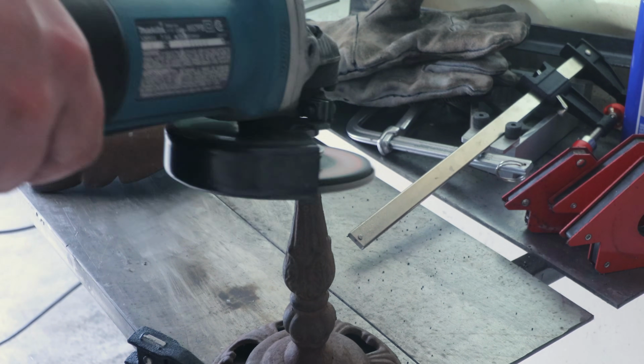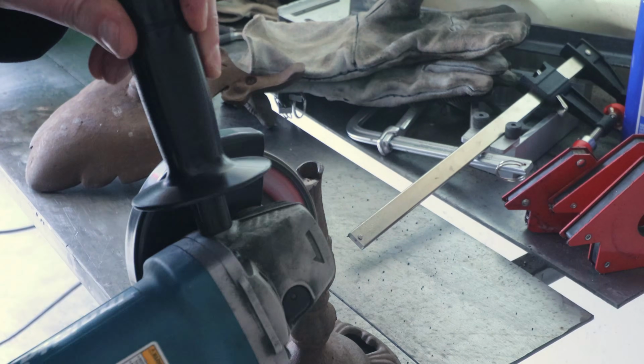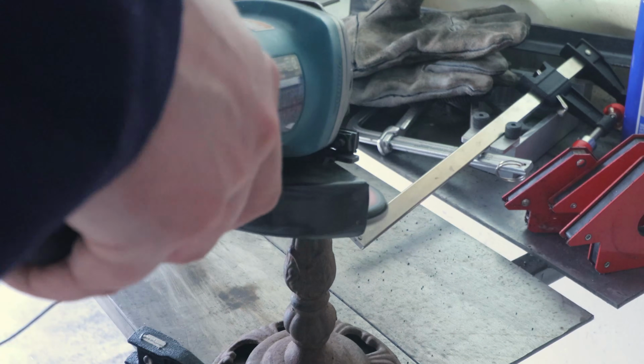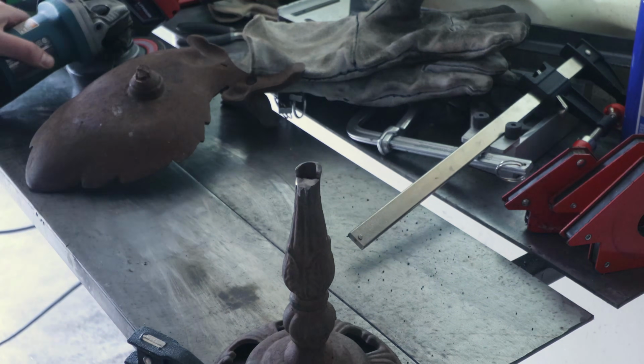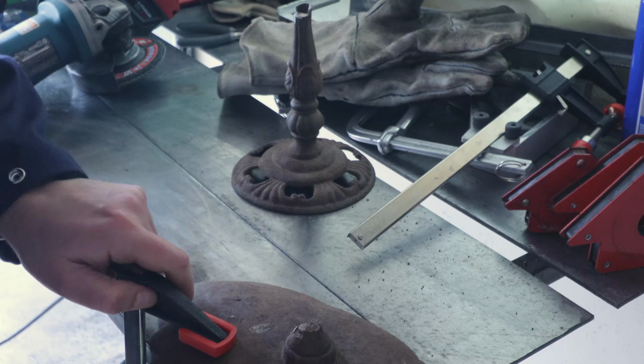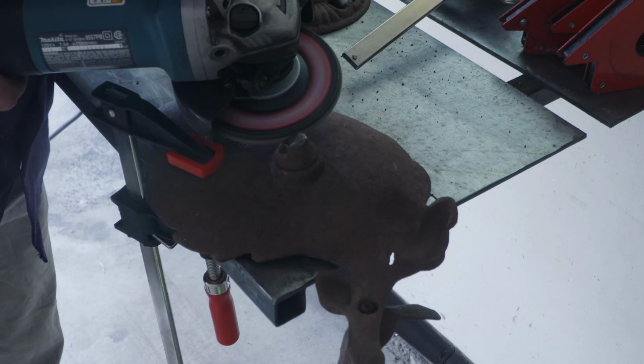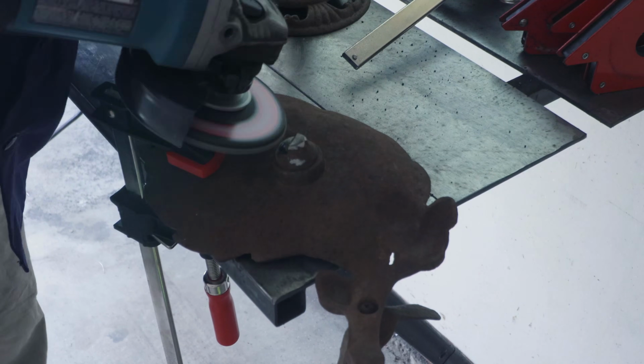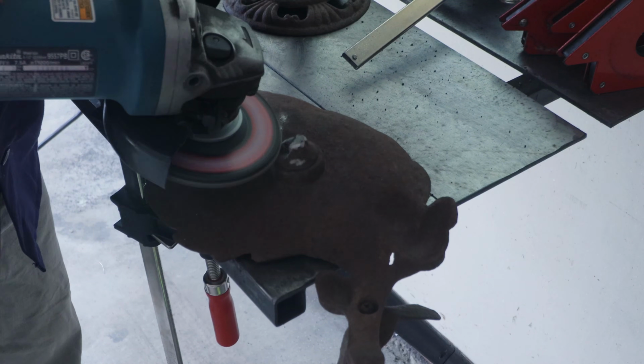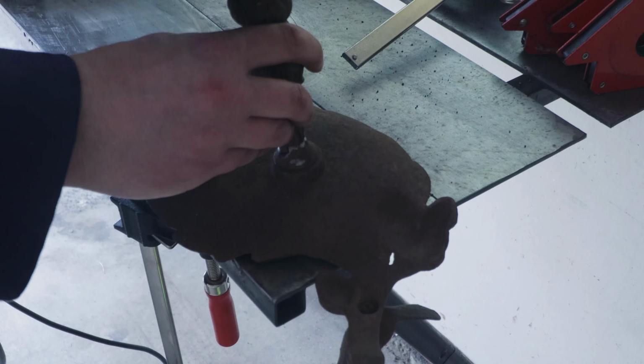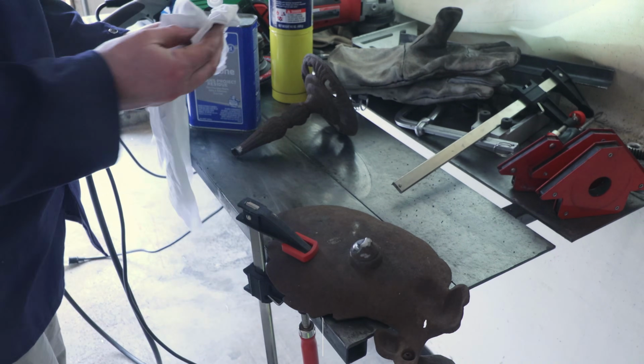Second, because cast iron has minimal ductility, preheat is important. If you introduce a lot of heat into a small area, such as what happens with welding, and then let the piece cool, cracking is very likely. Instead, a large area of the piece should be heated with a torch, and then the area in the weld zone should be heated to somewhere between 200 Fahrenheit and 750 Fahrenheit. After welding, the piece should be cooled slowly to mitigate cracking.